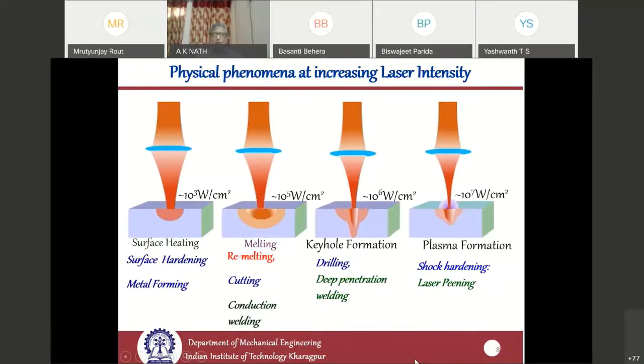When you focus the laser beam, depending upon the power density, you can realize various effects on a material. If the laser power density is in the range of kilowatt per centimeter square, relatively low, you just heat the material. By heating, you can realize laser surface hardening and metal forming, where the surface is not allowed to melt.